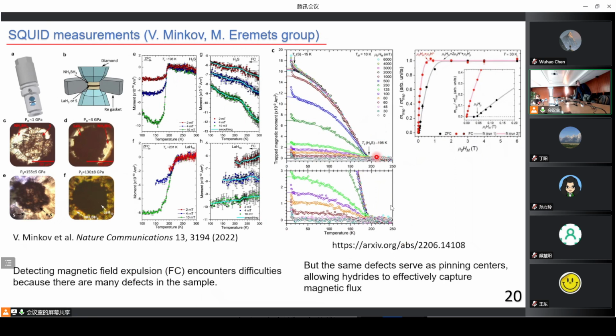They used a magnetic pulse in the superconducting state of hydrides. They applied a short magnetic pulse. And after this short magnetic pulse, they were able to detect, using this SQUID, trapped magnetic flux in the sample. And these trapped currents generated a magnetic flux which is much higher than the magnetic response detected without this pulse in the previous series of measurements using SQUID and the zero field cooling methodology. And it's very convenient to investigate the dependence of critical currents on temperature in a wide temperature region in such superconductors.